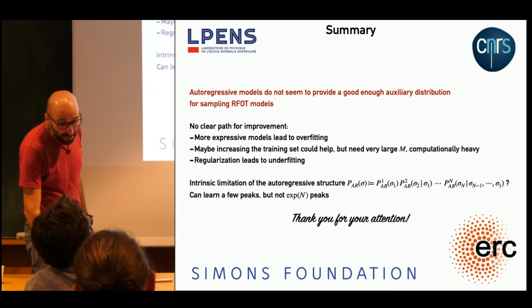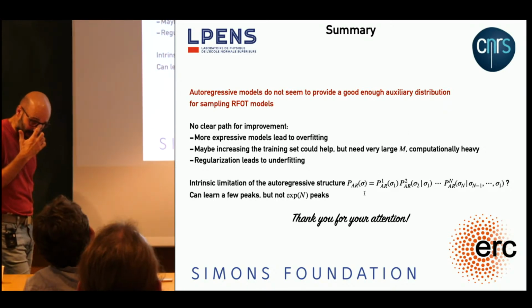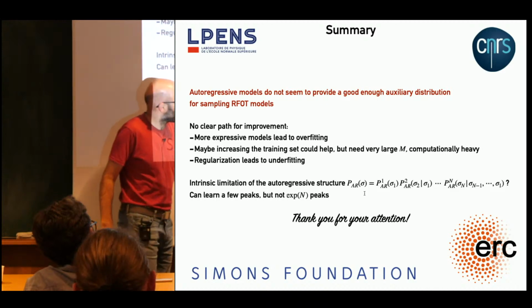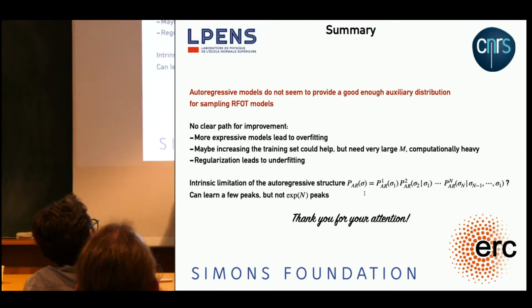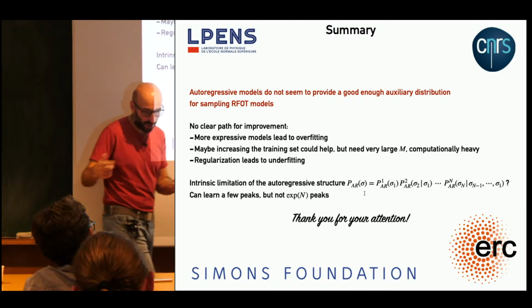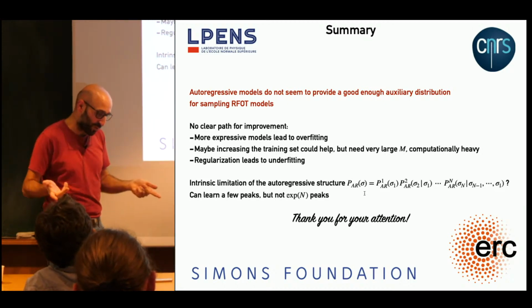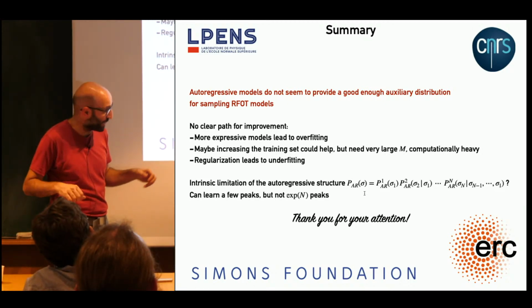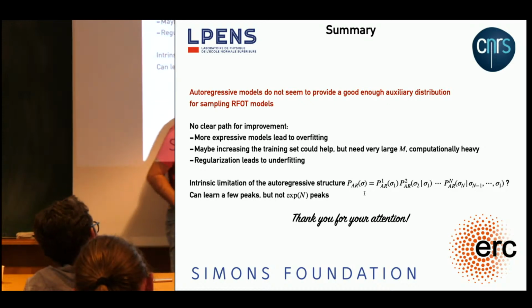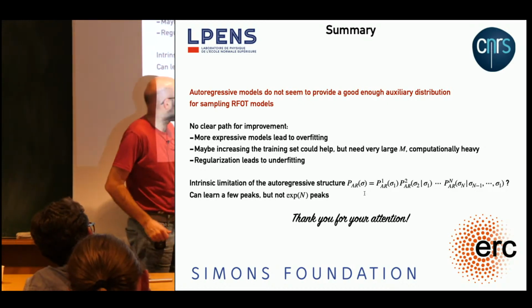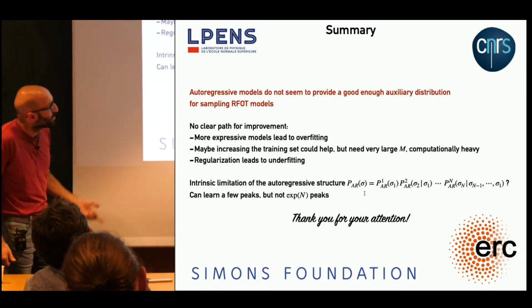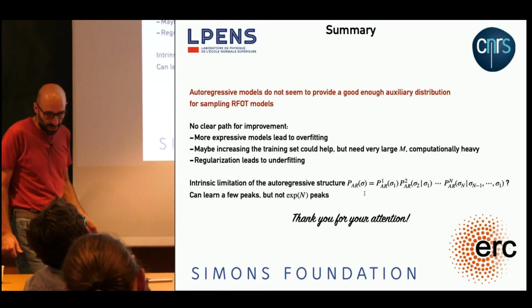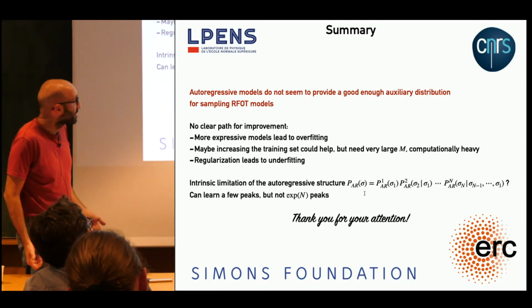My feeling is that there is maybe an intrinsic limitation of the structure that we chose. Because here you start by sampling one spin, then you sample the second conditioned on the first, and so on. But if you have a system with a lot of constraints and many different peaks, then maybe you cannot learn all the probability peaks in this way. It's possible that a better architecture could do the job, but we didn't have any idea.